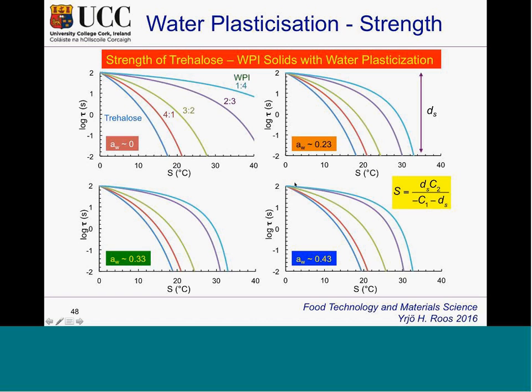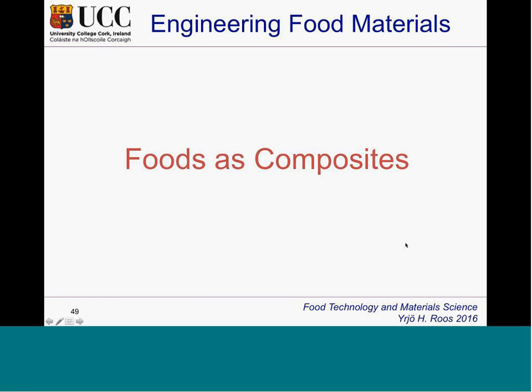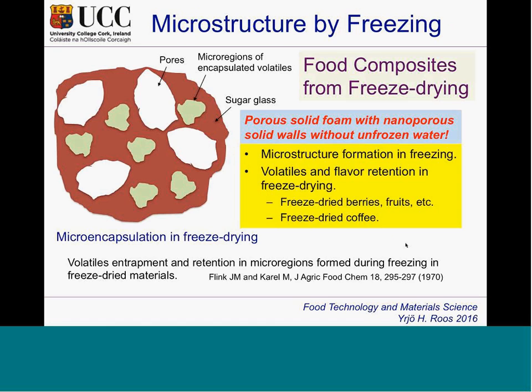We don't have too much time, but I would like to mention a few. Freezing, we certainly do, and if we freeze out the water, we could have limits of how the material was frozen, and we have sugar glass surrounding some dispersed phases. We could say that we have fairly good microencapsulation and protection of these components because they are surrounded by solid glass, and there was work done on that in early times. On the other hand, if we look at some of our data, it makes quite a big difference what sort of solids are in the material that we put in a freezer.